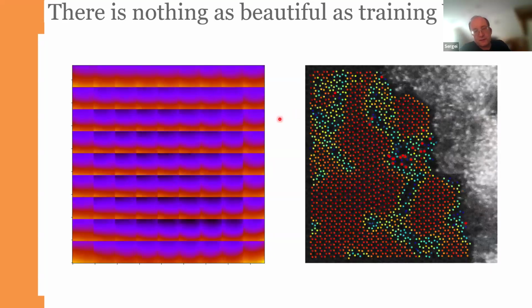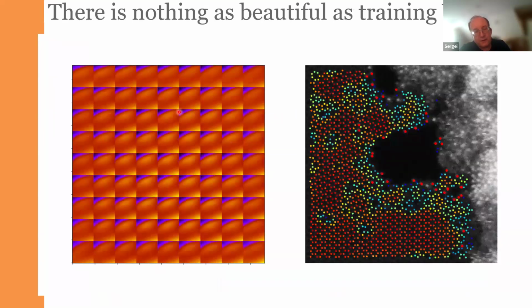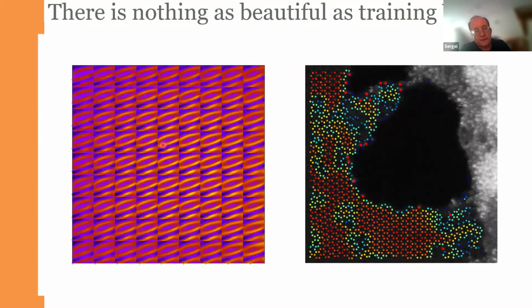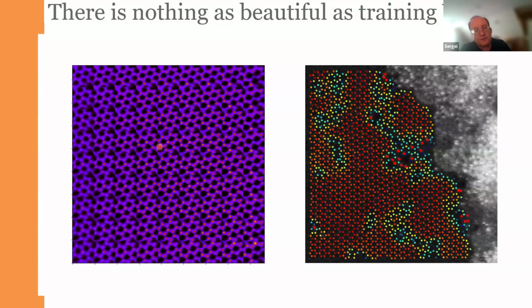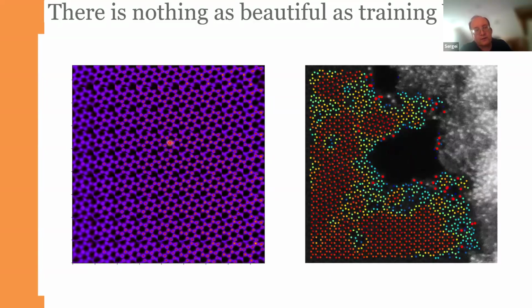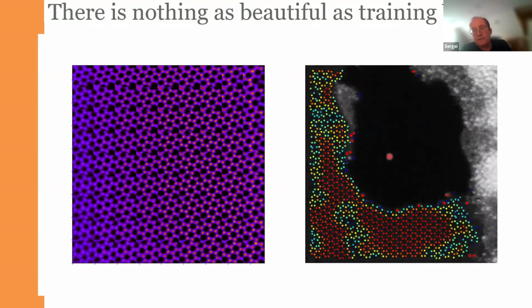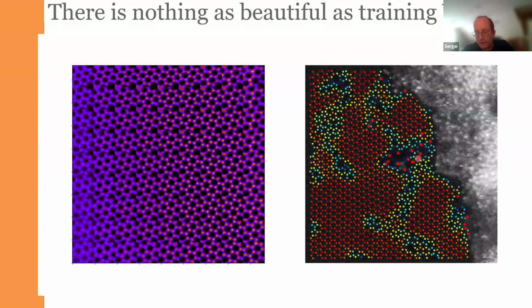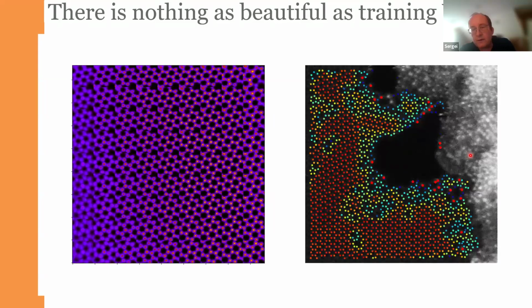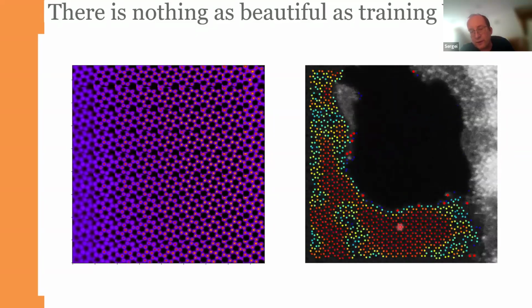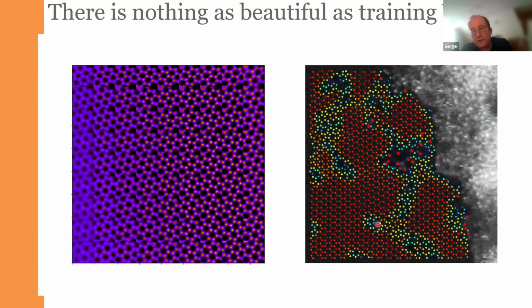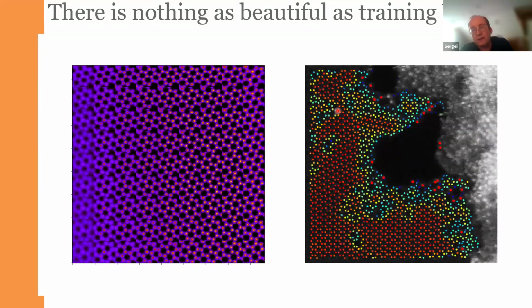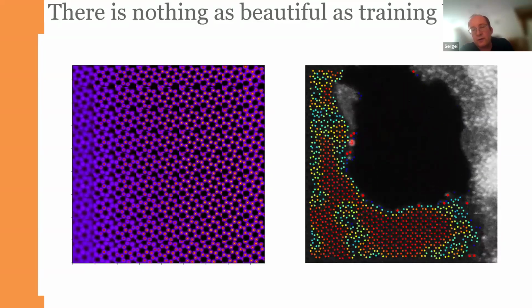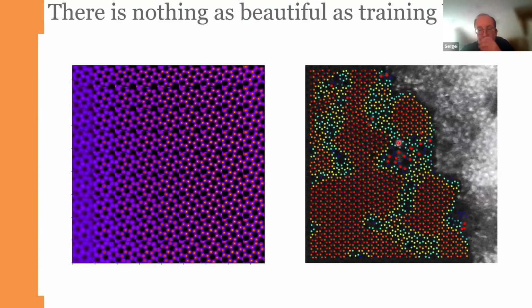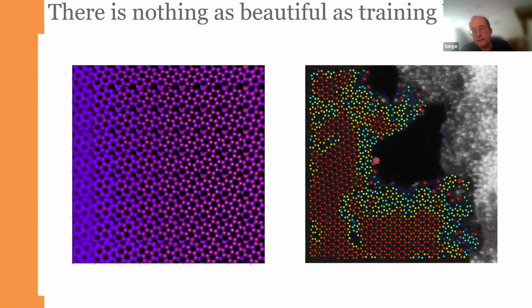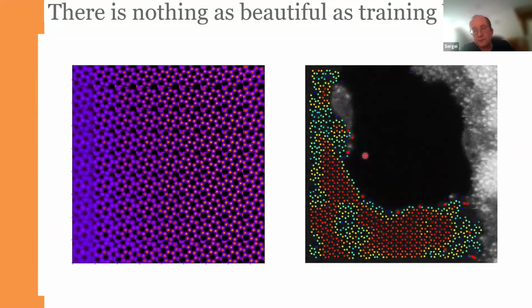So this is an example of how the VAE trains. So look at this part. You can see that first it learned to recognize the patterns in one direction, and then it locked in and started to recognize the structures of the local neighborhood. And this is the dynamic image when we use the video of the graphene evolving in the microscope. And we color it by the latent variable. So you see that we can now visualize the dynamics of these rafts of the ideal graphene and the behavior of the disorder, which evolves under the action of the electron beam. So if you're interested in the physics of graphene and the chemistry of graphene, it's all now visualized with the single atom distribution.